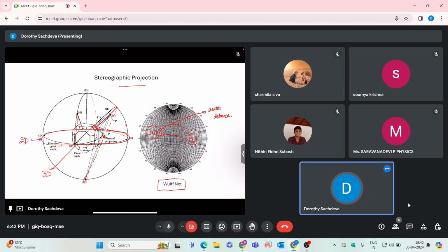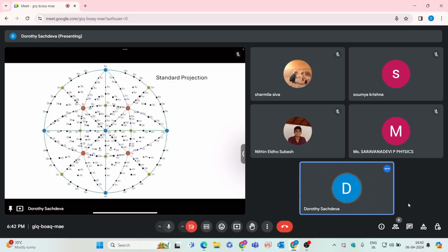So this is basically a standard projection where you can see that if your atom is along 0, 0, 1, the zone axis is represented by a direction, and direction is given by square brackets. So the central spot will be your 0, 0, 1 and the spots 1, 0, 0 and 0, 1, 0 will be 90 degrees to this plane and 90 degrees to each other. So in this zone axis 1, 0, 0 and 0, 1, 0 planes will be present. So here are those two planes and these two are 90 degrees. Also you will have the inverse of this, bar 1, 0, 0 and 0 bar 1, 0, also present,